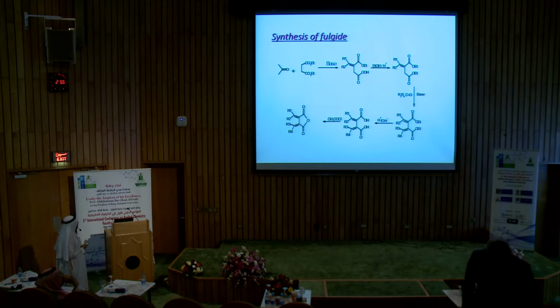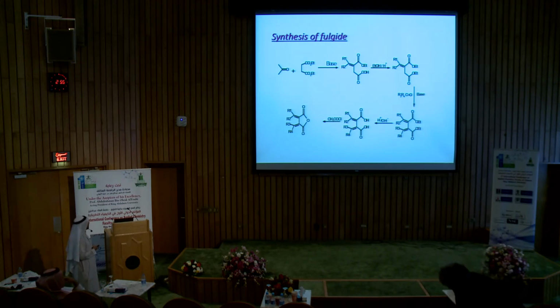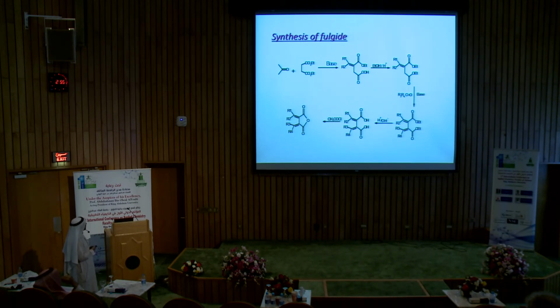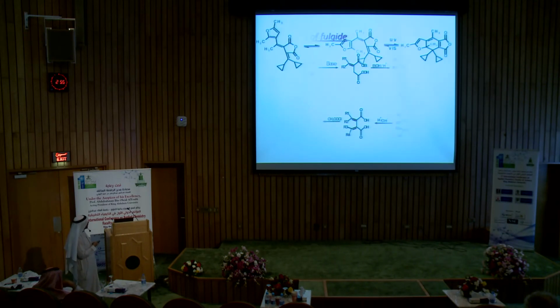Synthesis of fulgide. The fulgide can be synthesized through these routes, which is a multi-step synthesis starting from ketones, then condensation through Stobbe condensation with diethyl succinate in the presence of a base such as tertiary butoxide. Then we get the half ester. To activate the other methylene, we have to re-esterify it, and then the diester again goes through another Stobbe condensation using an aldehyde or ketone, whatever is needed. And then we get the half ester again, then hydrolysis of the half ester gives the diacid, and then dehydration of the diacid gives the fulgide.